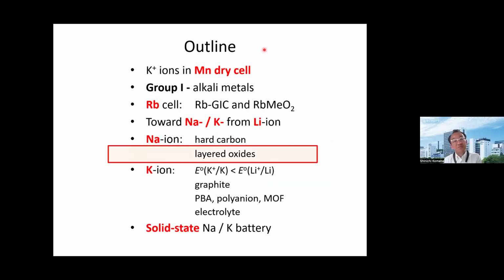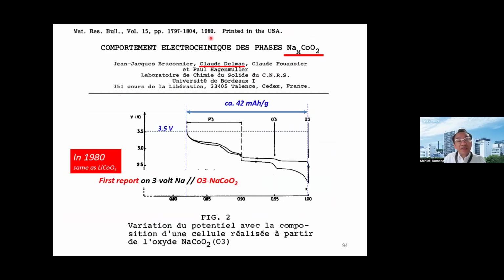Anyway, next, let me move on to the positive electrode, the layered oxide. In a very old paper in 1980, Professor Mizushima and also Dr. Delmas's group reported that layered sodium cobalt oxide shows highly reversible sodium insertion and extraction. But because of the low purity of the non-aqueous electrolyte solution, the upper cutoff voltage is just 3.5 volts. Because of the limited potential region, the reversible capacity is so limited. But please note that this is the first pioneering report of 3 volt sodium cobalt oxide, a layered oxide.